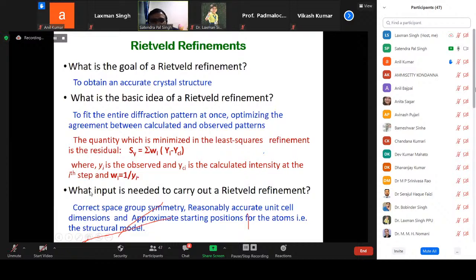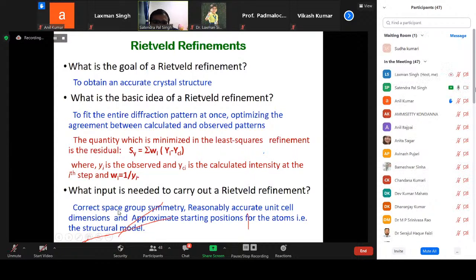What are the inputs needed to carry out the Rietveld refinement? We need the correct space group symmetry, reasonably accurate unit cell parameters, and approximate starting positions for the atoms. That is the structural model. So these are the initial conditions required to start the Rietveld refinement.